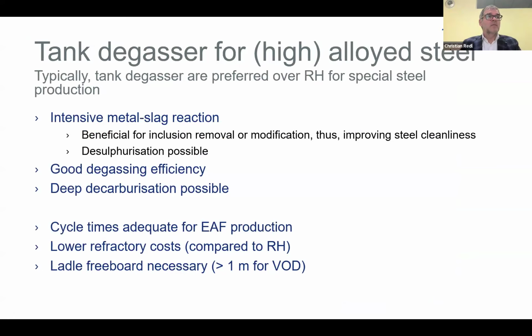So why is the one more suited for integrated mills and the tank degasser mainly used for high alloyed steel grades? There is an intensive metal slag reaction possible for the tank degasser, which is not possible at the RH because you're inserting the snorkels, so you're only circulating the liquid steel, without a big slag reaction. In the tank degasser, you have an intensive metal slag reaction, which is beneficial for the removal or modification of the inclusions, and therefore improving the steel cleanliness. With the slag, we also have a very good desulfurization during the vacuum treatment, a very good degassing efficiency, and we can make a deep decarburization.